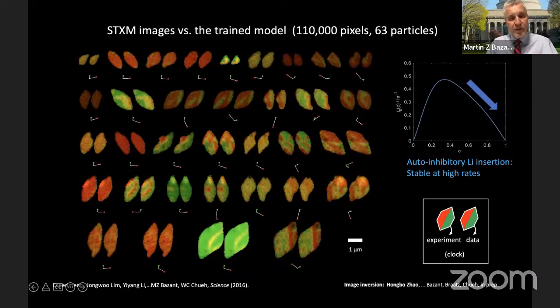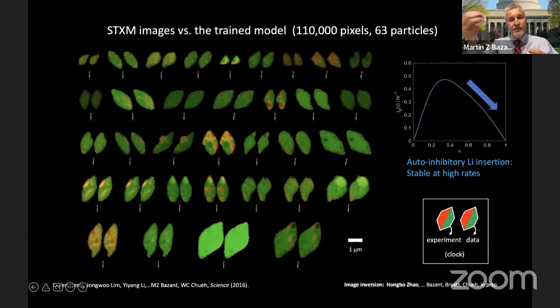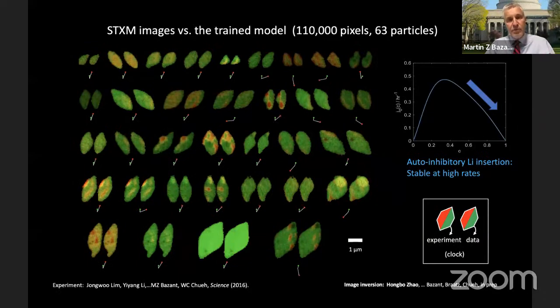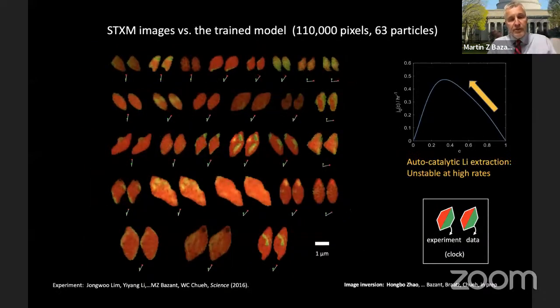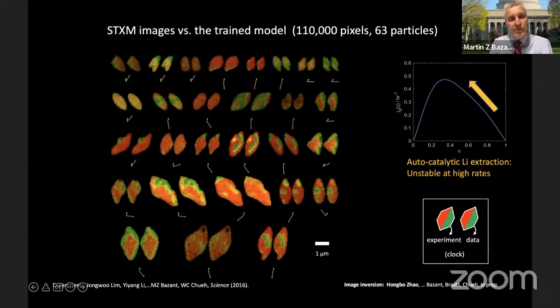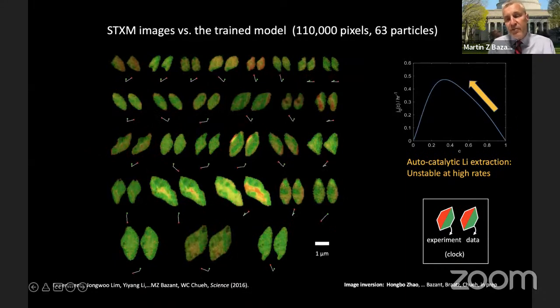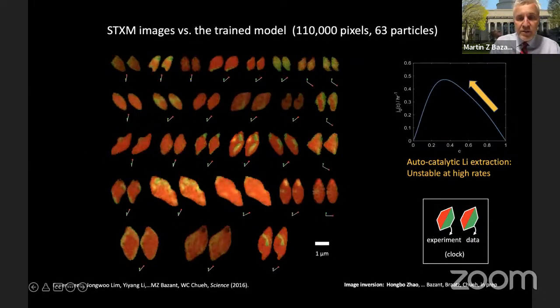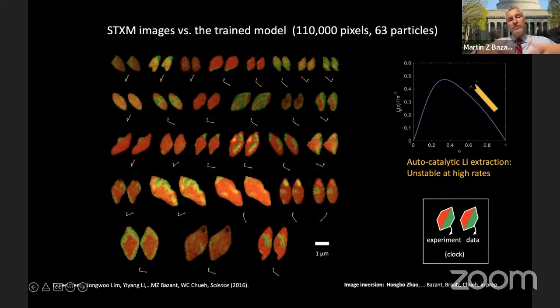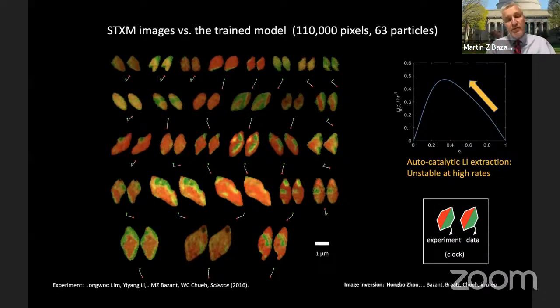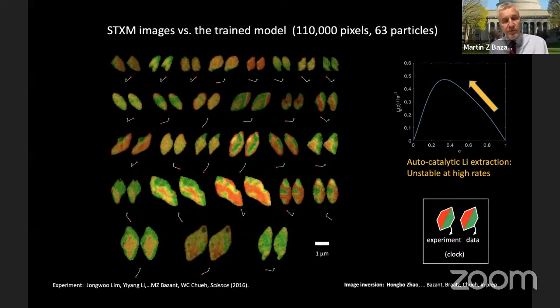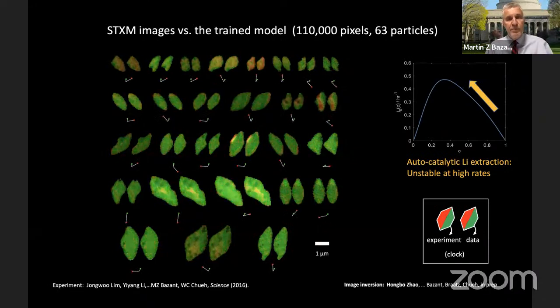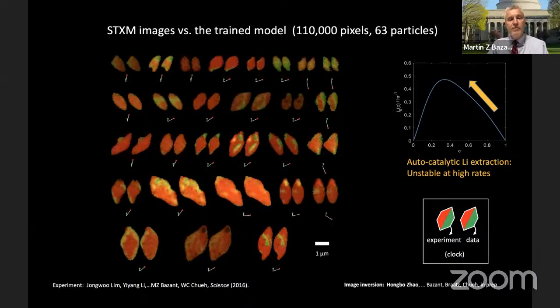And in fact, what we're seeing right now is insertion. If you just look with the naked eye, you see that it's fairly uniform. But if I jump ahead, here's extraction of lithium from the very same particles. And notice it's just obvious with the naked eye, there's much more pattern formation going on, because in that direction, the rate is autocatalytic and hence is destabilizing, and you're forming patterns more easily. Whereas when you insert lithium, you're suppressing pattern formation. Very consistent with the theory.